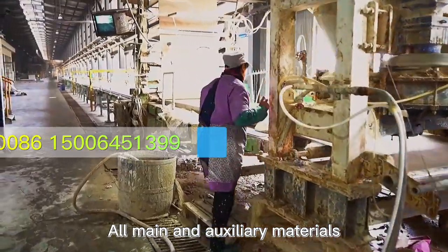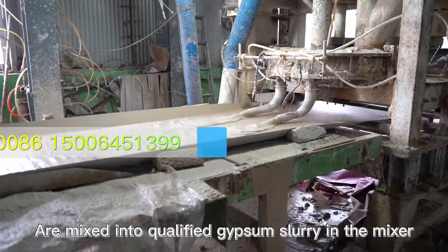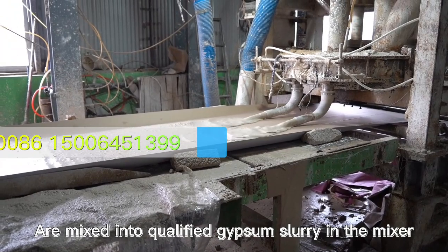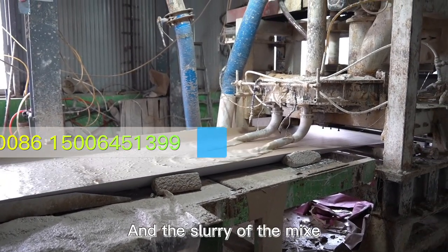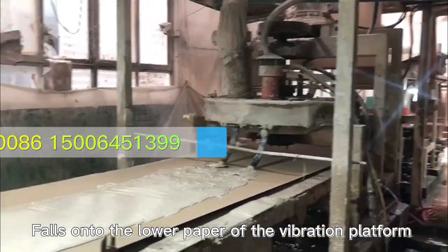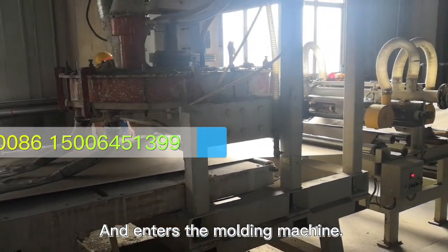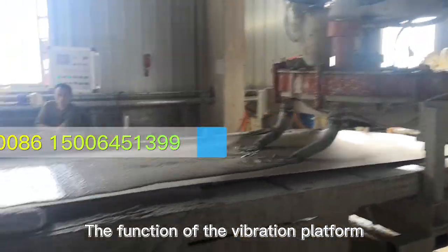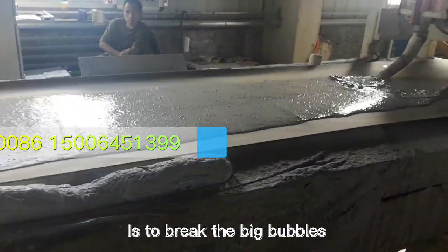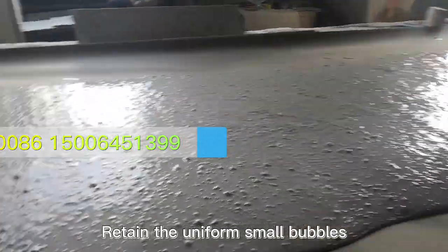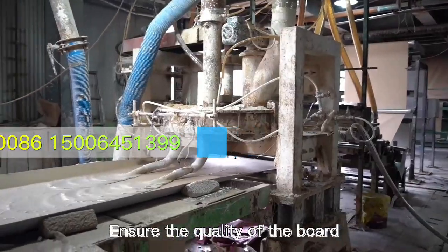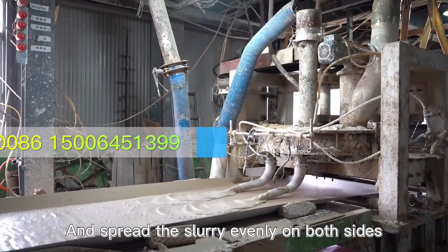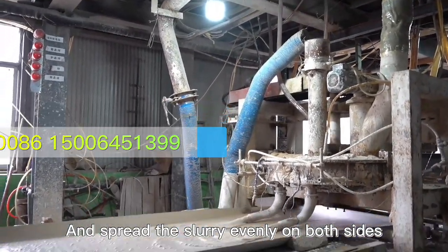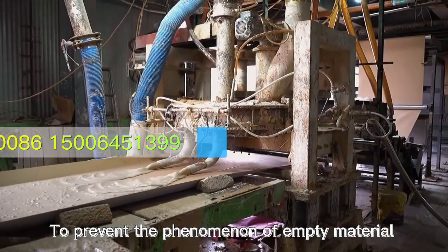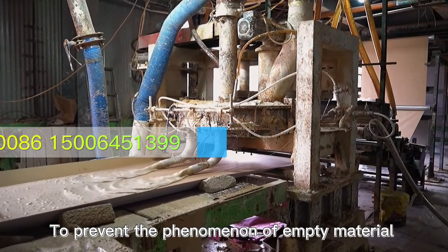All main and auxiliary materials are mixed into qualified gypsum slurry in the mixer, and the slurry of the mixture falls on the lower paper of the vibration platform and enters the molding machine. The function of the vibration platform is to break the big bubbles, retain the uniform small bubbles, ensure the quality of the board, and spread the slurry evenly on both sides to prevent the phenomenon of empty material and leakage